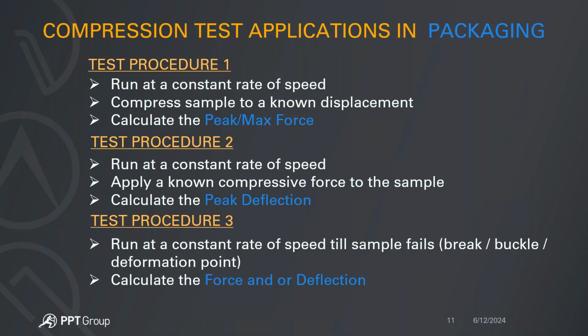And then in test number 3, this is more of a destructive test where you run at a constant rate of speed until the sample fails or it breaks or buckles or it reaches its point of deformation. And then at that point, you can calculate the force at the point of failure and also the deflection at the point of failure. Now, again, depending on what the industry actually requires, whether you're testing to an ASTM standard or an ISO standard or your own internal standard, you're likely to fall under one of these 3 test types.